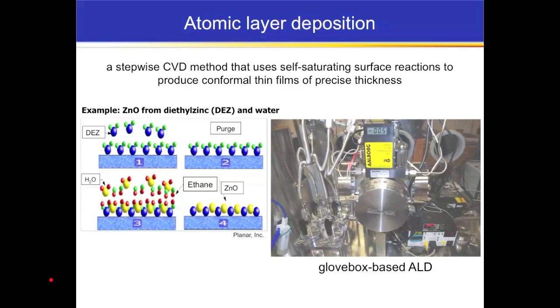If you're not familiar with ALD, it's basically a stepwise CVD approach that uses self-saturating surface reactions to make very, very nice, high-quality, conformal thin films on pretty much any surface you might want. So if you wanted to make, for example, zinc oxide, you might use diethyl zinc and water for your chemistry. And the ALD process consists of basically exposing your surface to diethyl zinc. You get a monolayer adsorbing to the surface.